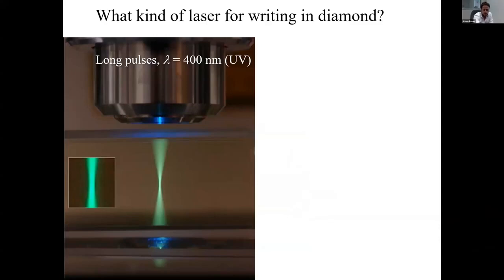The question is, what kind of laser could be used for fabricating in diamond? And here, this is a very nice picture taken from an MIT talk. What it shows is essentially a blue laser, a laser in the UV, incident on a vial containing a fluorescent dye. And what you can see is that you have this focused Gaussian beam, which is coming in roughly in the blue. And you can see this green fluorescence, because this is a fluorescent dye, wherever you have the focused Gaussian beam. It's a beautiful picture, but this means that we can't have very nice pinpoint 3D processing. We have absorption throughout the Gaussian beam, and so we can't have this precision three-dimensional nanofabrication using linear absorption.